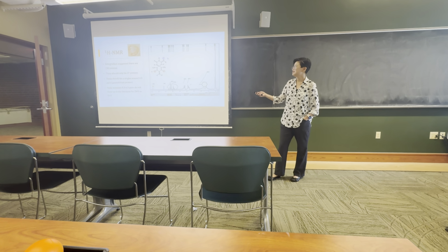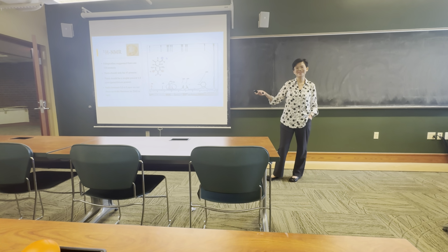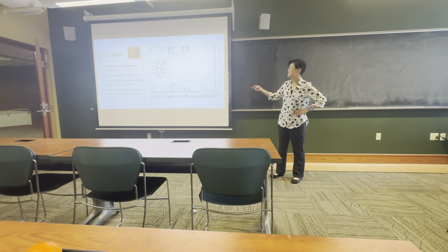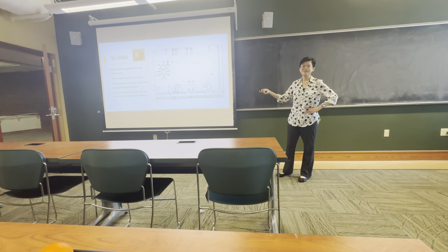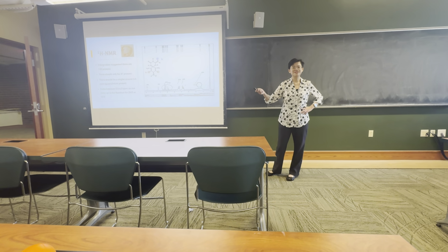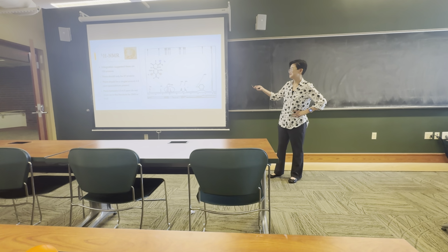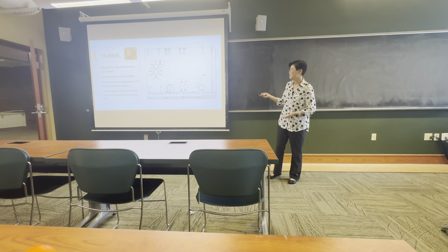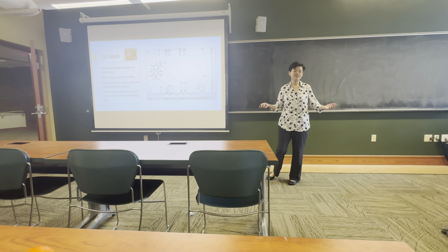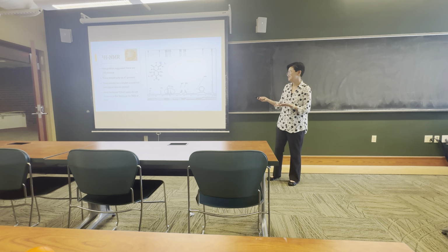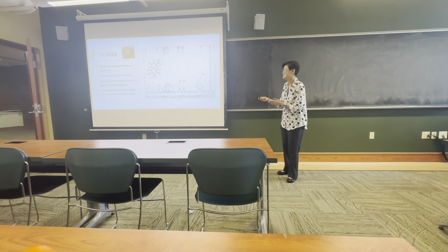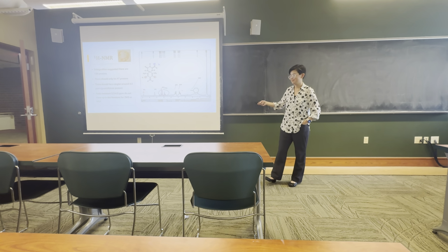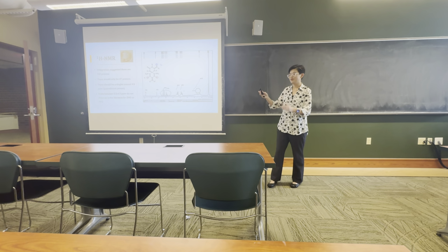Something you'll notice is it doesn't look as nice as the product on the last few slides. It's not that nice bright red color. I actually took this NMR a semester later, and it turned a different color, and it wasn't crystalline anymore. So as you can imagine, the proton NMR isn't the best. My integration suggests that there are 130 protons in the molecule, but there's only supposed to be 47 protons, which is problematic. But again, this was a semester later, and something probably happened to it over winter break.